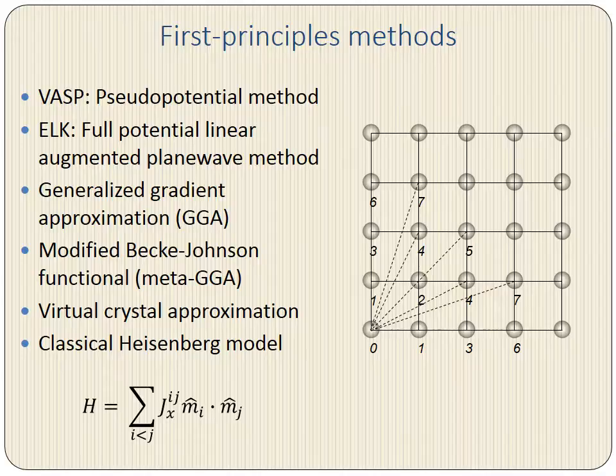For magnetic doping, we directly substitute manganese for zinc in our supercells, while for hole doping, we use the virtual crystal approximation, in which we substitute our barium atoms with a fictitious atom of fractional charge to impart holes into the system. Finally, when we start discussing the magnetic exchange, we obtained our parameters by fitting our total energy calculations to the classical Heisenberg model. The way this was done is we took two manganese atoms and then placed them at various neighbor distances, such as you see in the image on the right. We then calculated the total energy for a ferromagnetic alignment and also an antiferromagnetic alignment. We did this for the different neighbor pairs, and then we collected all those energies together and fitted them to our model, allowing us to extract the coefficients.